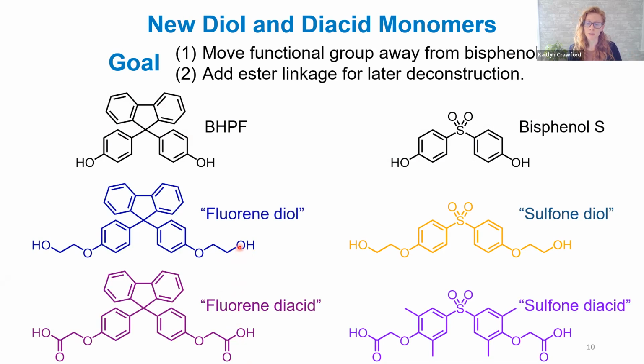So we could join the fluorene diol and the fluorene diacid and make a polymer, or the fluorene diol and the sulfone diacid and make a polymer, and so forth. And so we'll just briefly show you a couple of examples that we've made in our lab to demonstrate that these monomers can be polymerized and that we can, to some degree, control the glass transition temperature.